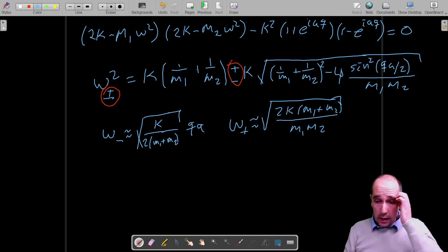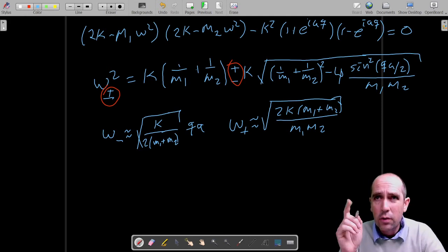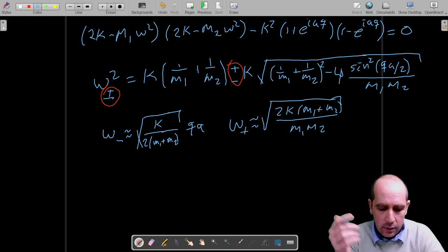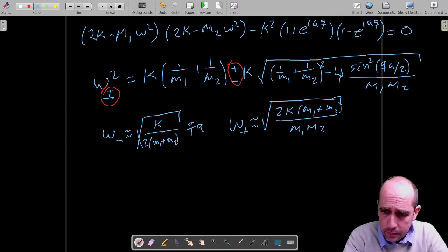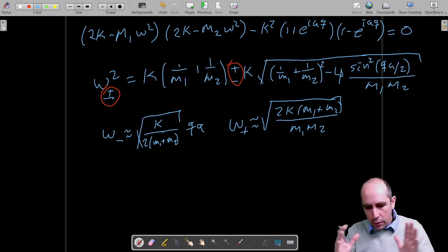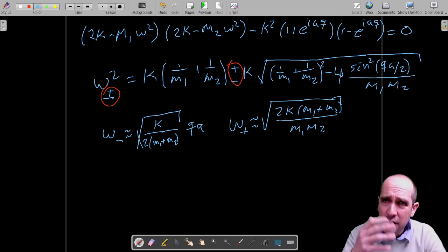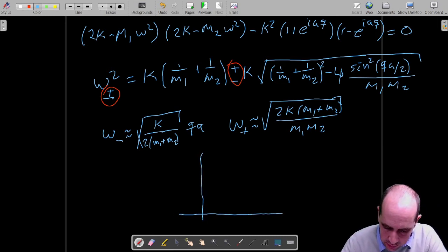Okay, and this means that in the vicinity of q equals 0, q, the equivalent to the wave vector of this collective oscillation of atoms in the crystal, which now we know, because it solves the equation, behaves like a plane wave. So the phonons, these vibrations of the lattice, produce plane waves that propagate through the crystal, something similar to what happens in the case of electrons. And we essentially get two possible solutions in the vicinity of q equals 0, which we can draw like this.